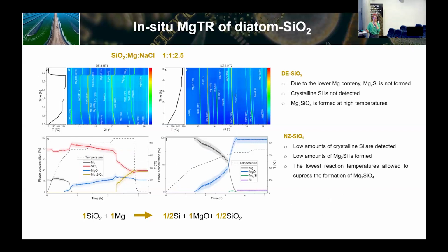So then we also changed the ratio, and we saw that if we change the ratio, we start seeing magnesium silicate. So we also tried to play a bit to promote these reactions, to see why we have these materials. If the reaction is at 650, then you would not have this magnesium silicate. And at the synchrotron, we were at about 800 degrees. We didn't see the magnesium silicate, so we said, let's heat it a bit more to see if it reacts, and we have this reaction product, and we heat it more, and then we have it.